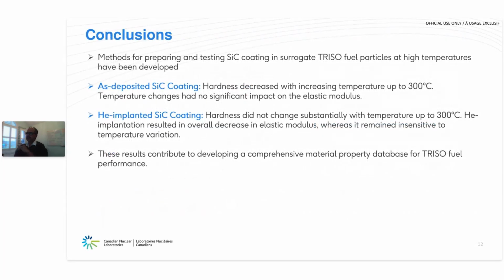So to conclude, we're developing methodologies for sample preparation and testing of these coating layers. In particular, what I talked about today was silicon carbide coating on surrogate TRISO fuel particles for high temperature measurements. For as deposited silicon carbide coating, hardness decreased with increasing temperature up to 300 degrees C. Temperature changes had no significant impact on the elastic modulus.